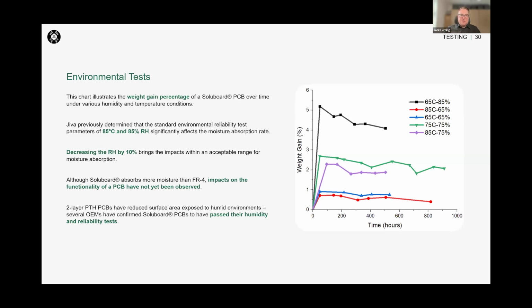So we've actually found that by decreasing the RH by 10%, this has a significant improvement in terms of the moisture absorption of our material. And this reduction doesn't actually have any negative repercussions for the users of our material. We have also been able to demonstrate that our two-layer PTH PCBs are even less susceptible to the humid environments that they might be in because of the reduced surface area. And we have multiple OEMs now who've put our material through these reliability tests, and they have passed consistently.